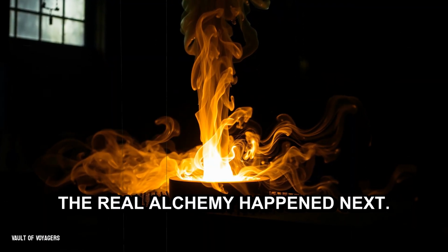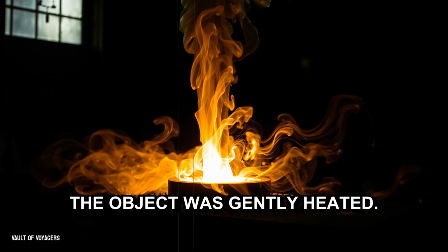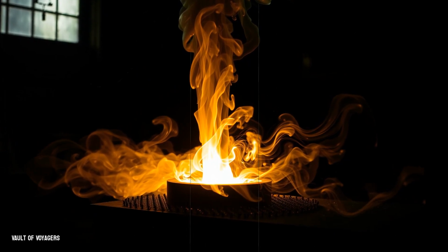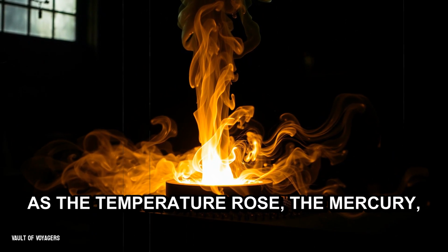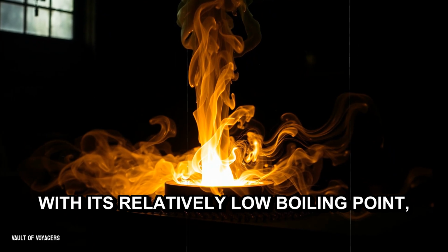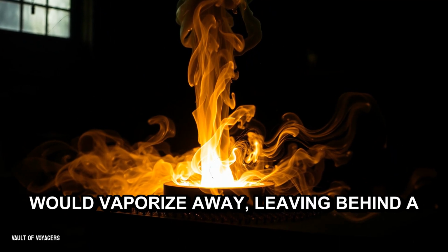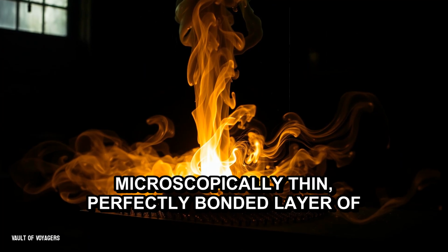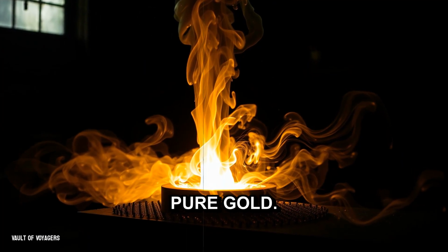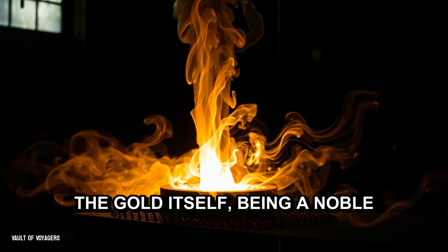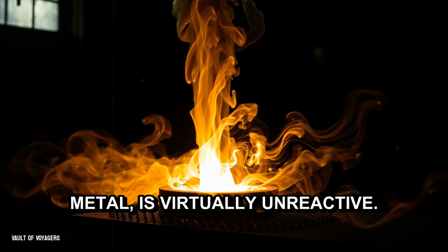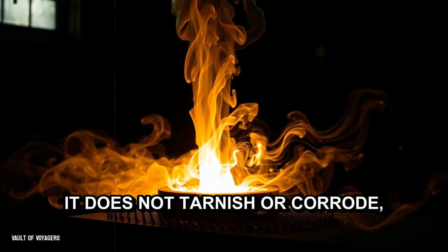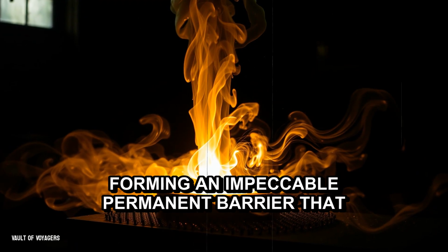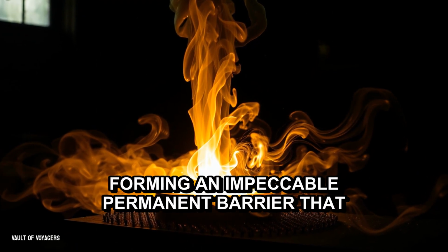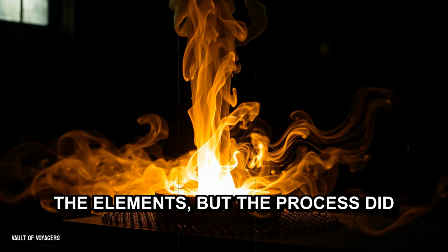The real alchemy happened next. The object was gently heated. As the temperature rose, the mercury, with its relatively low boiling point, would vaporize away, leaving behind a microscopically thin, perfectly bonded layer of pure gold. The gold itself, being a noble metal, is virtually unreactive. It does not tarnish or corrode, forming an impeccable, permanent barrier that protected the base metal beneath from the elements.